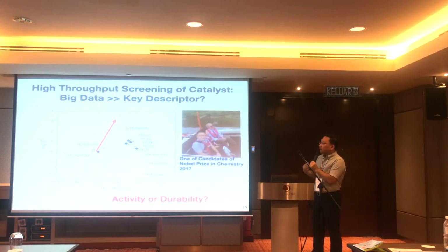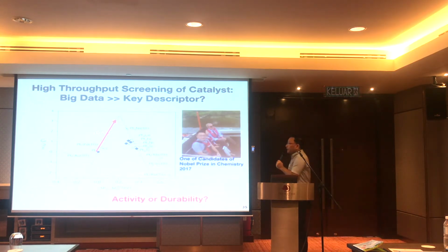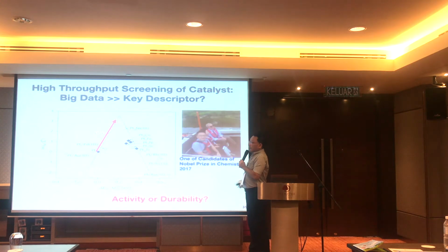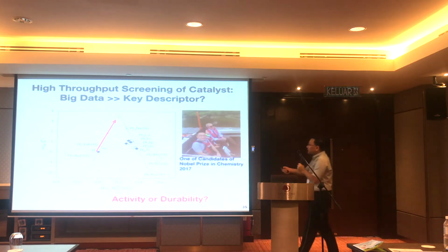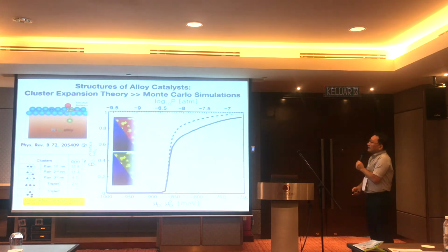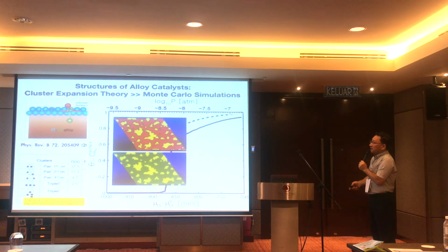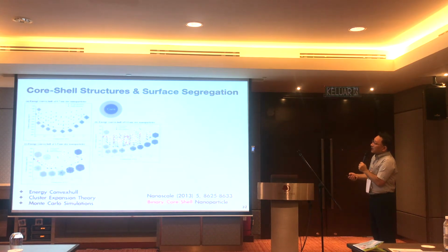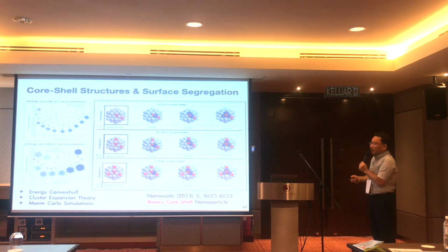Provided insight how to develop new materials by utilizing only one single descriptor, but was not commercialized. This is Norskov. The issue is that there are strong segregation issues. For example, platinum nickel, platinum cobalt, each was provided by Norskov. They are very good actually. The activity is very good. The problem is the segregation of core material into the surface.